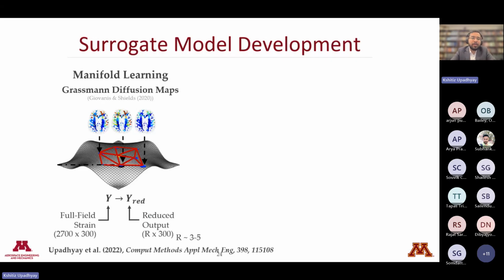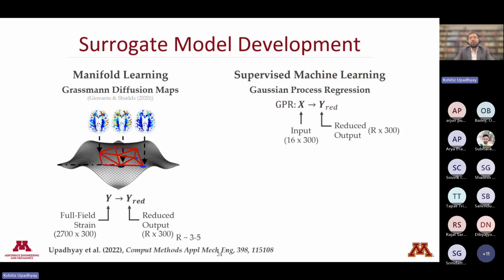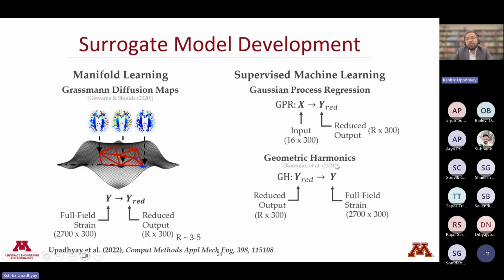So this two-step dimensionality reduction method reduces the dimensionality of the strain fields down from 2700 to actually 3 to 5. So these 3 to 5 numbers would now represent the information in the full strain field, which is a huge dimensionality reduction. Once we have the reduced data, we used GPR, or Gaussian process regression, to train this model between input and the reduced output. And we also trained a geometric harmonics model to recreate the full data by training a model between the reduced output and the full field strain. Together, the GPR and the geometric harmonics model create our full surrogate model, where if you now have any set of input parameters, you can find out the full strain fields using these two surrogate models.